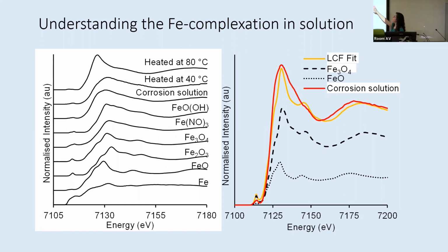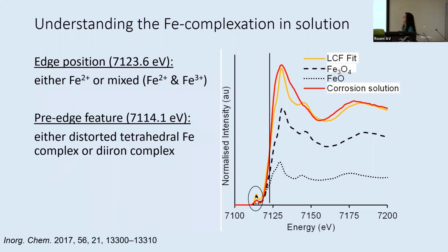But what's sort of interesting is you can see that we kind of just have a combination of iron oxides and binding in the solution. But what's more interesting is that we can actually start picking apart our data and use heat to better understand what's happening in terms of the coordination of that iron in solution. And that's critical in terms of understanding how that iron is interacting with any of our species, because that may play significant impact in terms of the degradation sequence we would see.